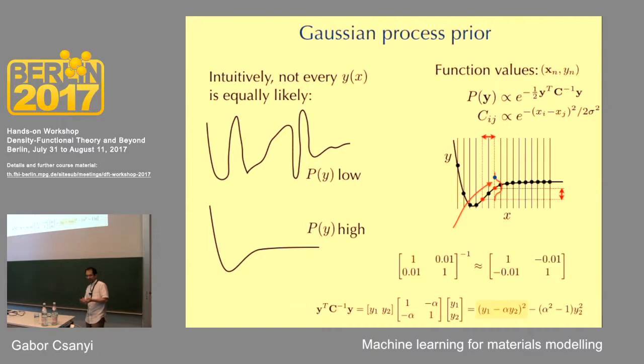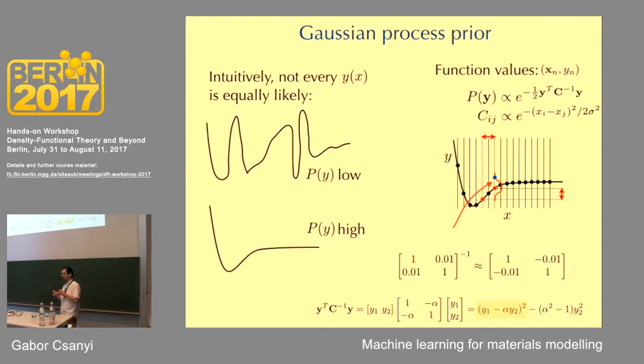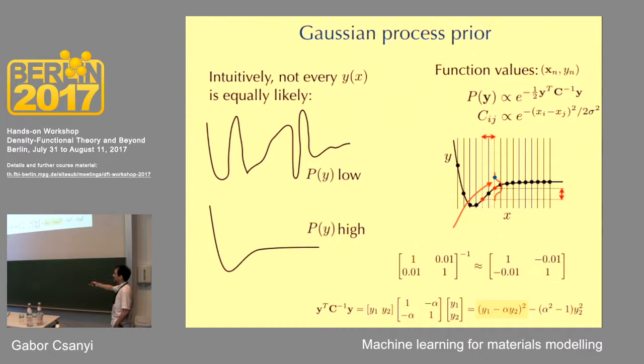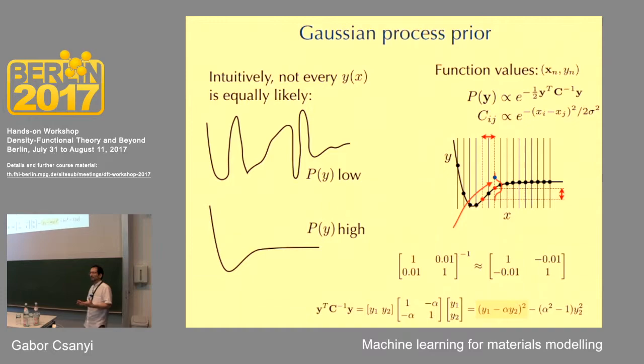There is a lot more mathematics here. The key questions are: how do we transform the coordinates — that's the problem of representation; what kind of kernels do we use; and how do we get data? The kernel choice relates to what the potential energy should look like. There is a way — using a probabilistic idea in function space — to assign high probability to smooth functions and low probability to jagged ones. Going through that mathematics, you discover that this statement is related to the kernel: the basis function we use to build our approximation is intimately related to what we think are high probability functions.